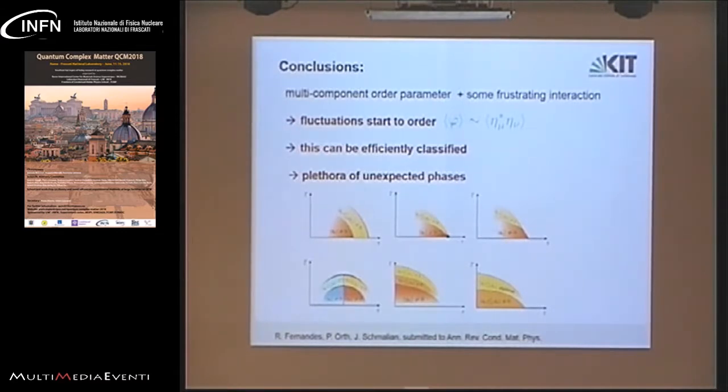If you look at the anisotropy of the resistivity as a function of temperature, before iron selenide was even investigated, we predicted how it would look in a system with that vestigially ordered state when the Néel temperature was 0. And basically the data lay on top of a calculation that was done something like 3 or 4 years before the measurements were done.